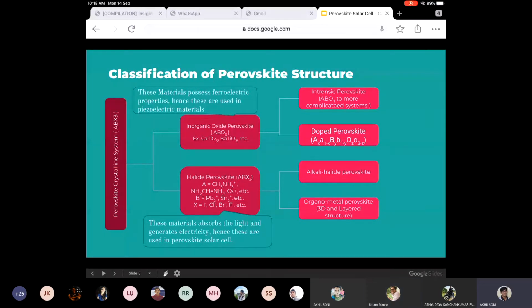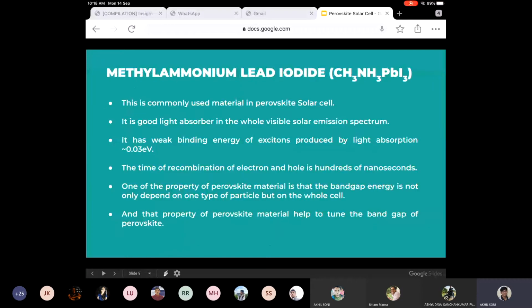Sir, it has weak binding energy of the exciton produced by light absorption. It is approximately 0.03 electron volt. The time of recombination of electrons and holes is hundreds of nanoseconds. One of the properties of perovskite material is that the band gap energy depends not only on one type of particle but on the whole cell, and that property helps to tune the band gap of the perovskite material.